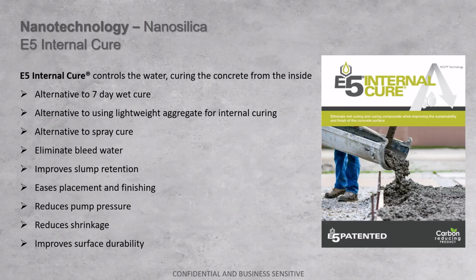The elimination or reduction of bleed water prevents the migration of that water to the surface, increasing the water to cement ratio and lowering the durability on the surface, right? That prevents those migratory paths from being there after the concrete hardens, which allow pathways for moisture and other things to climb or travel into the concrete and cause deleterious effects to the concrete matrix and the steel. So they had seen benefits of reduced shrinkage, reduced cracking, and they had experienced the benefits on the job with accelerating the construction schedule, right?